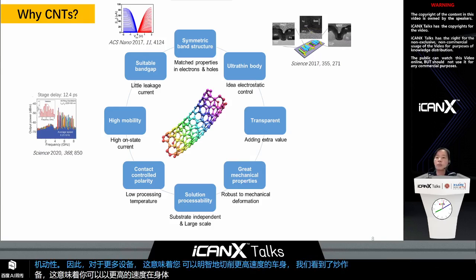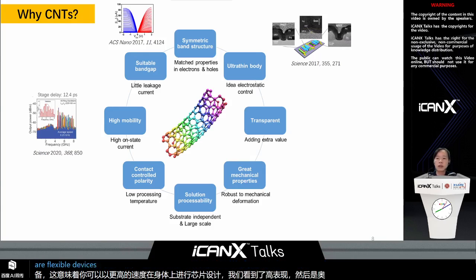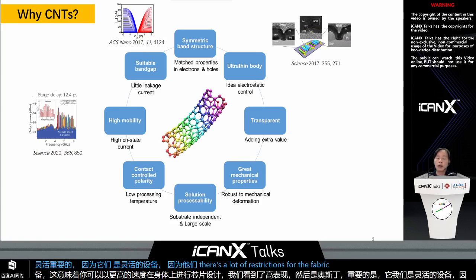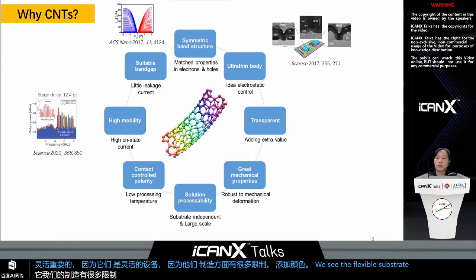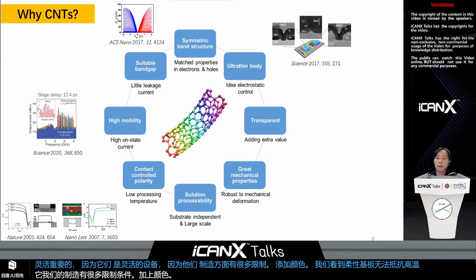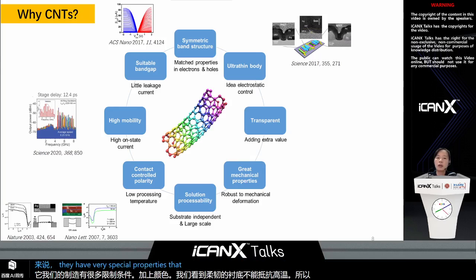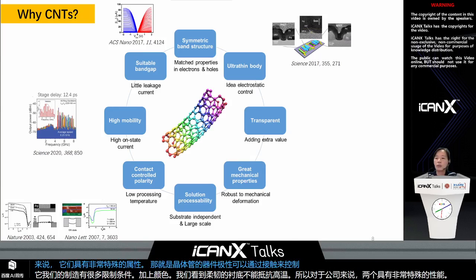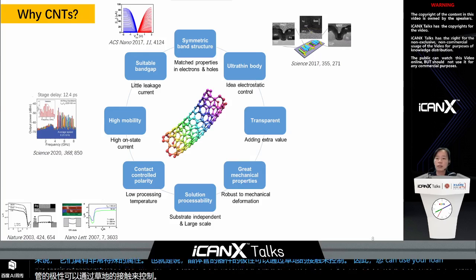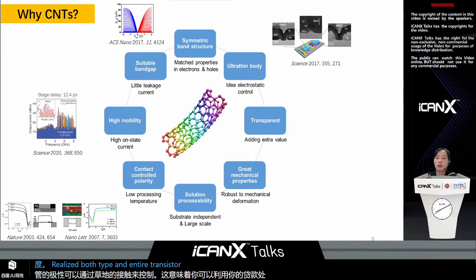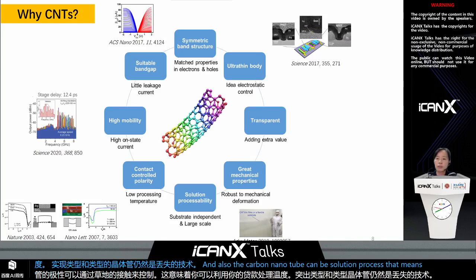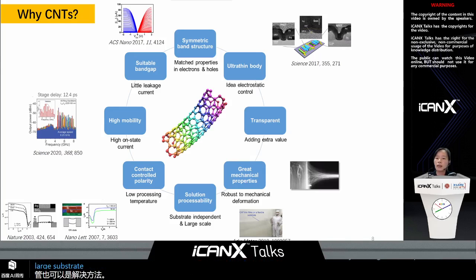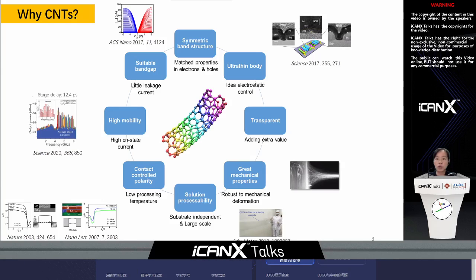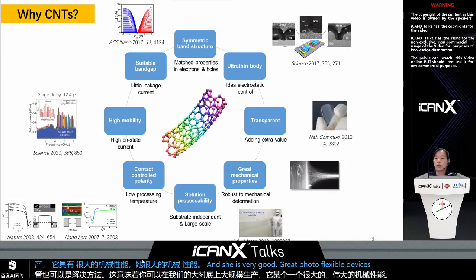For the devices, that means you can achieve much higher speed, or high performance. And most importantly, for flexible devices, there are a lot of restrictions in fabrication, because polymer or flexible substrates cannot resist high temperature. Carbon nanotubes have very special properties: the polarity of the transistor can be controlled by the contact metal. That means you can use a low processing temperature to realize both P-type and N-type transistors for CMOS technology. Also, carbon nanotubes are solution processable, which means you can get mass production on a large substrate. They have great mechanical properties, which is great for flexible devices, and they are also transparent.